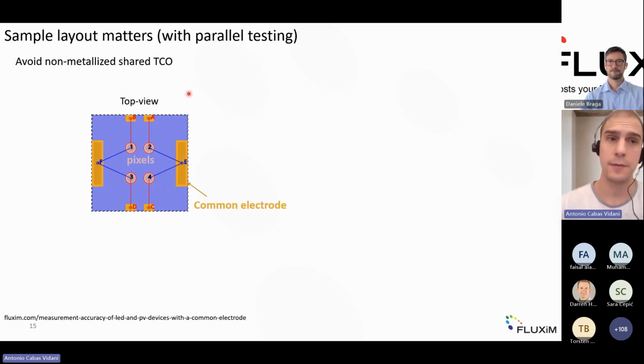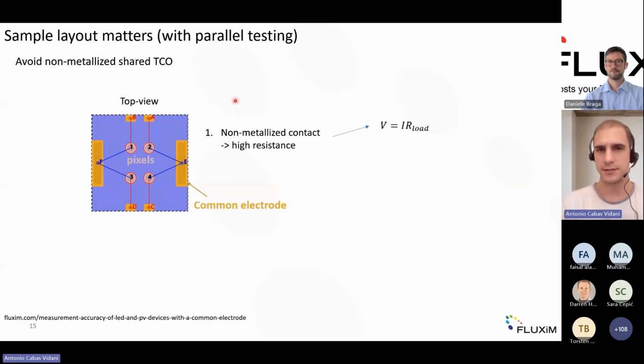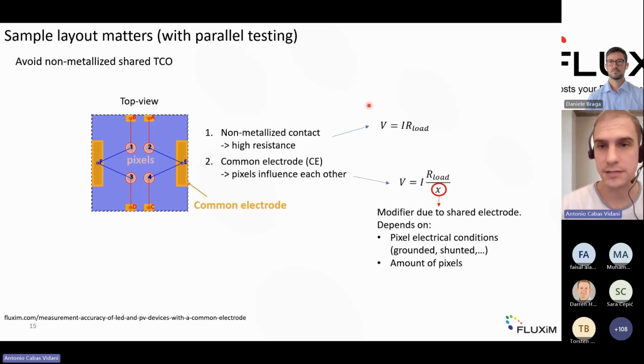And it also happens that this electrode is non-metallized. Now, why is this a problem? Well, if it is not metallized, then we have a higher resistance, and this leads to a deviation of the voltage you measure. So you don't effectively measure the real VOC or MPP of your pixel. And then if you have a common electrode instead, here you have an influence that is a bit more difficult to quantify, because it depends on the electrical status of the neighboring pixel, and it also depends on the total amount of pixels connected to that same common electrode.